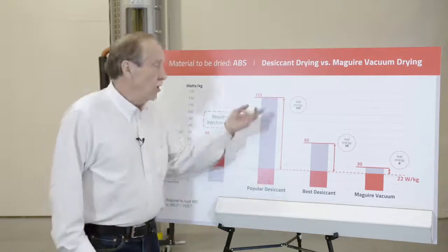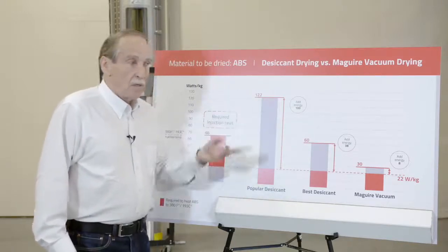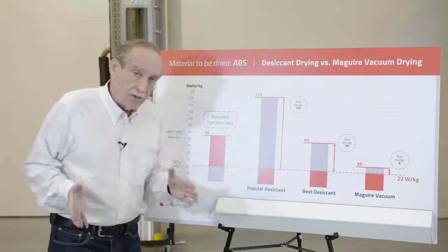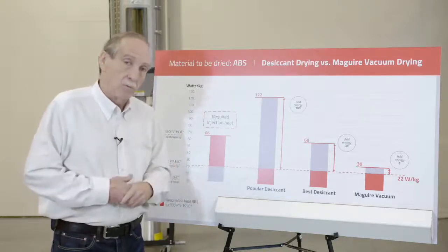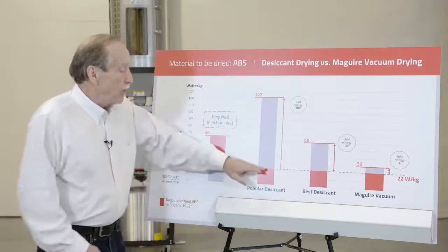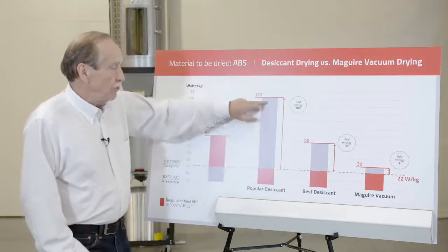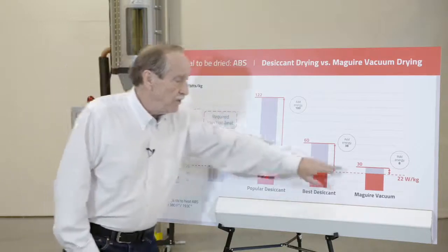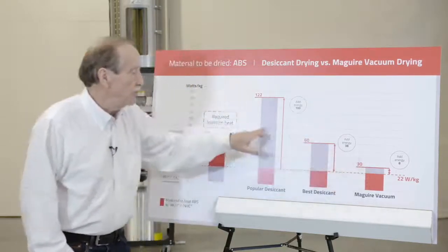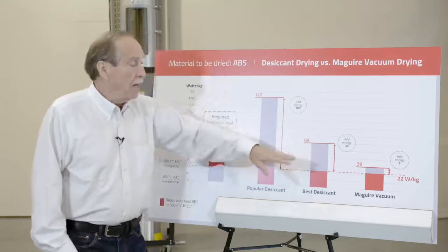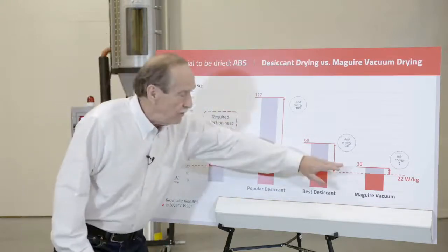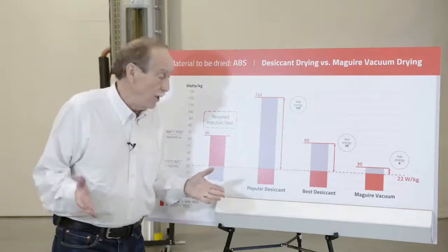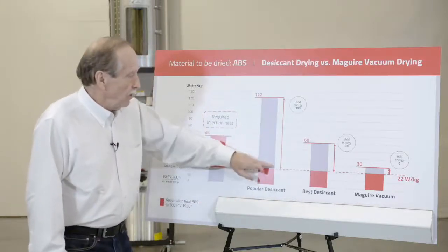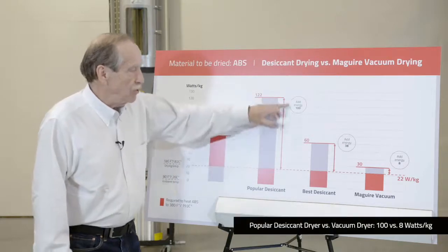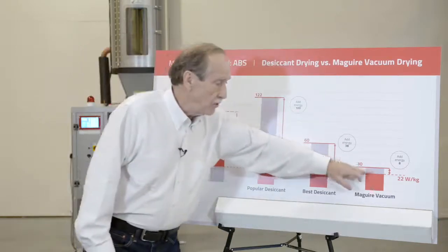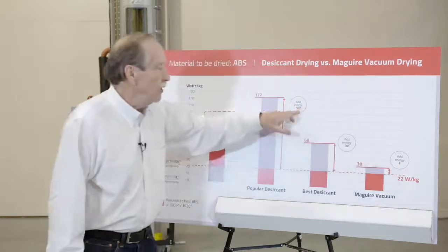Now, if you go back 10 years, 122 was a good number. And it's still considered a pretty good number, apparently, because that's the number one dryer that's sold. But this is your energy use with this one, and this is our energy use. And I'm just going to compare these two, because hardly anybody has this one. And even there, we're better. But I'm going to compare it to what you're probably running now. This added energy is 100 watts per kilo. This added energy is 8. We're running 8, you're running 100.